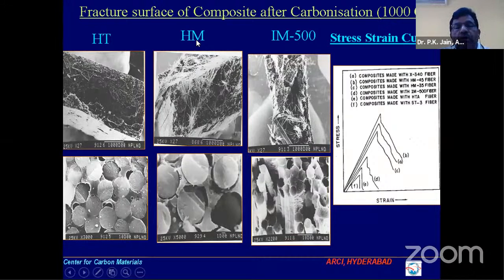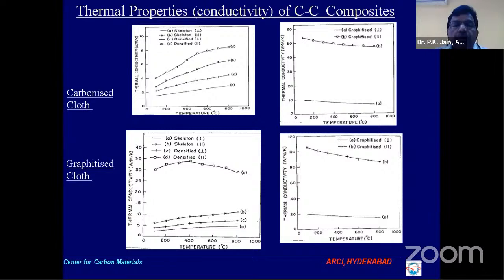Whereas the high modulus fiber, which has a gap between the two, these gaps will force the fiber to pull out, and eventually you will get a high strength in the fiber composite. And intermediate modulus gives intermediate properties, and this is the indirect correlation of the fiber matrix stress strain curve. The thermal properties are also like that.